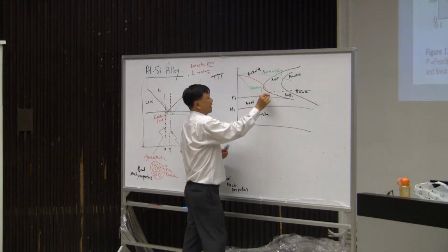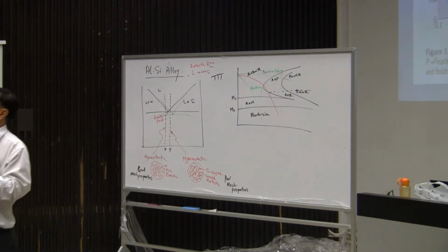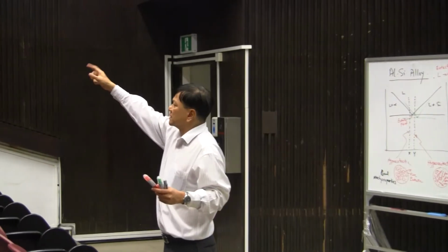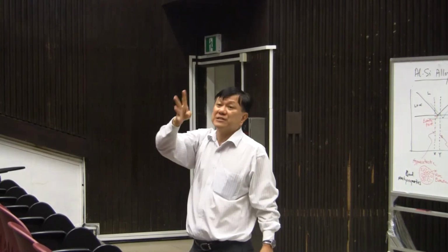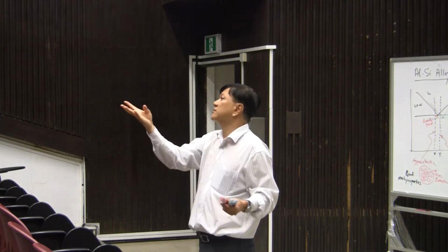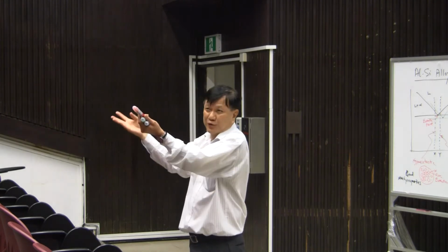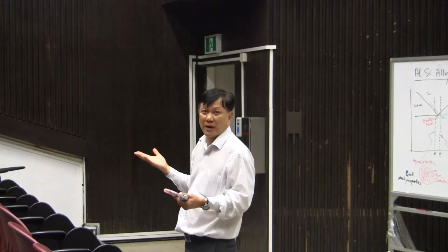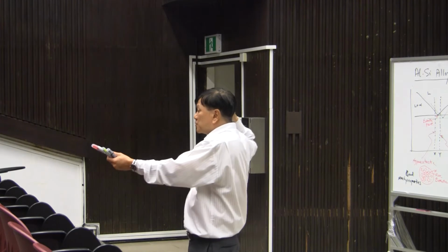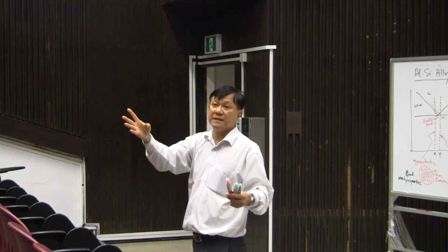Some of you who do the, what do you call it, the 1050, you quench in water, but you cannot harden. Correct, no? You cannot get 50 HRC. Some of you, in fact most of you, didn't harden the steel. Why? Because you need to actually cool it very fast to fully harden it.